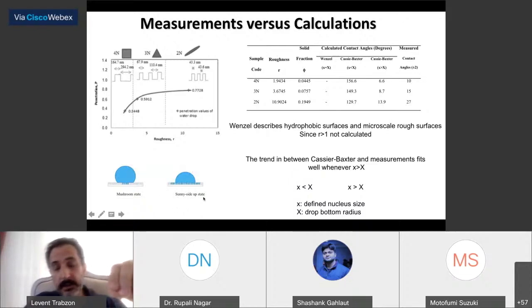Actually, such a finding is very well matched with the biological findings, and the much higher biological activity or osteogenic change of the mesenchymal stem cell we have seen in the previous slides. It is well agreed with the previous results. We also studied penetration, which I'm not mentioning too much, but it changes with the roughness. Again, that will also use Cassie-Baxter, but in the case of small x bigger than big X.